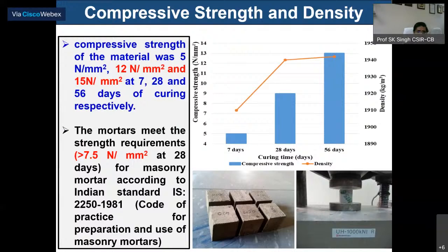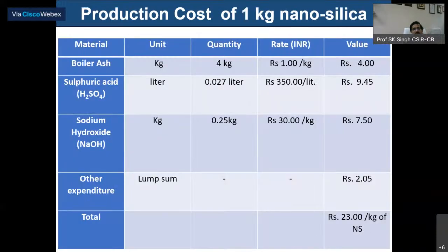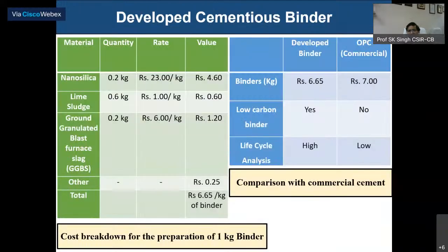So this is the strength. We are achieving good strength in different studies with lesser and maximum utilization of our lime sludge. If you look at the nanosilica, 1 kg of nanosilica will cost about 23 rupees if you make it in the same plant, as against more than 150 to 200 rupees a kg from the market. And when we make our binder, it costs about 6.65 rupees per kg, in place of more than 7 rupees per kg for ordinary Portland cement.